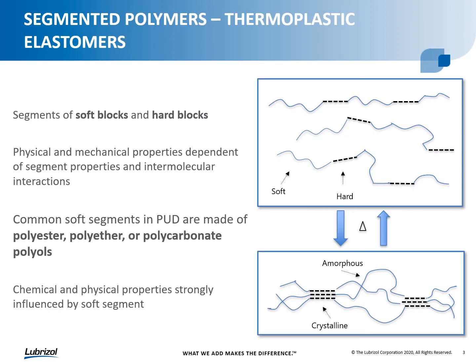Polyurethanes are segmented polymers or thermoplastic elastomers where you have alternating hard and soft segments. The hard segments are formed by the reaction of isocyanates and the polyols, and that hard segment is really responsible for cohesion of the material. The soft segments are typically a low Tg oligomeric polyol, and these are responsible for providing flexibility to the polymer. So you can see this alternating hard and soft linkage. And the common soft segments in PUDs are typically made up of either polyester, polyether, or polycarbonate polyols, which we'll see on the next slide, each with their own set of inherent strengths and weaknesses.